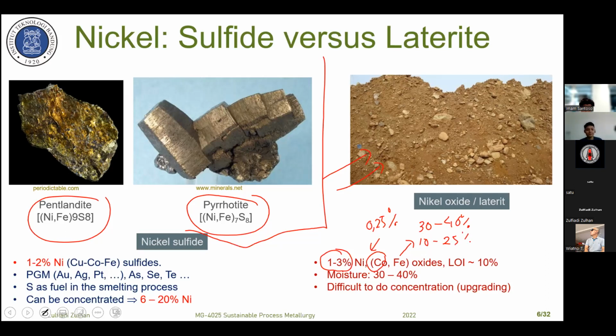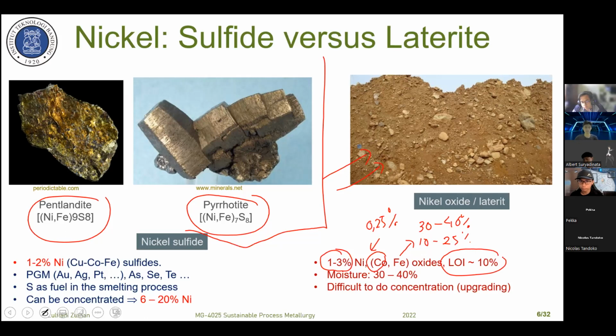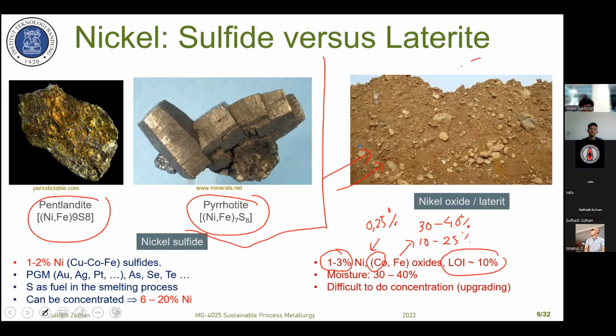And there's also crystal water, around 10% to 15% maximum. This ore always contains water, always moisture inside. The moisture content is between 30 and 40%. And for this ore, until today, people have tried to make a concentrate, but it was not successful.